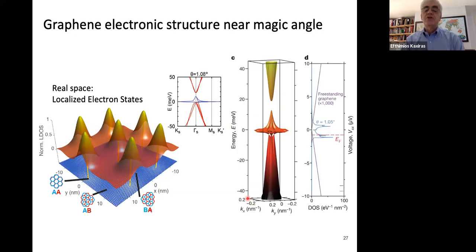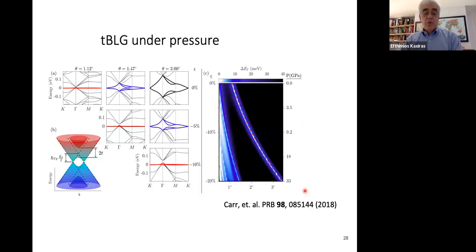Here's another picture. So here are the Kx, Ky components of the wave vector. And here are the bands in a two-dimensional space, which can be quite flat. And flat bands, of course, correspond to high density of states. So you see here the high density of states associated with this. And for comparison, the graphene density of states must be multiplied by a factor of 1,000 to be visible on the same scale. So with these realistic and accurate calculations, we can do more interesting things.